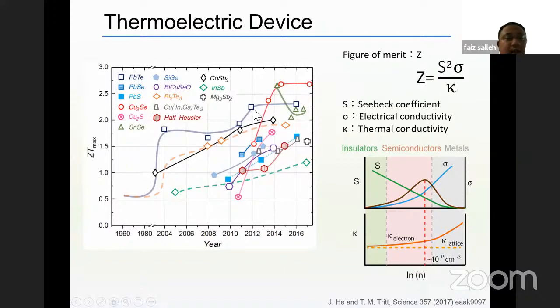In this graph, which shows the dimensionless figure of merit, ZT, multiplied with the average temperature as a function of the year, we can see that right now at the experimental level we can have up to 2.5 something. I think this is based on data until 2017. And the conventional ones use telluride-based materials, so it's around 1 to 2 something dimensionless figure of merit.